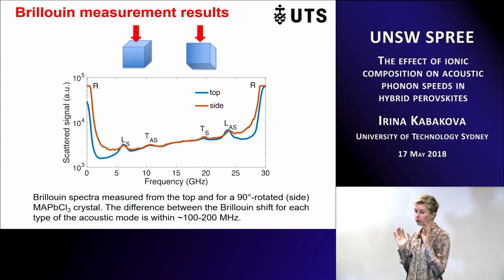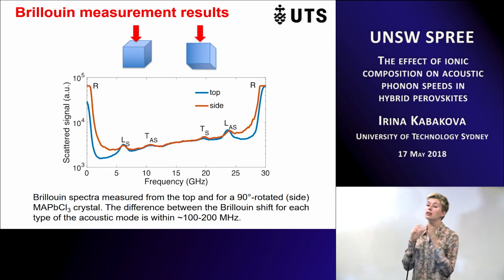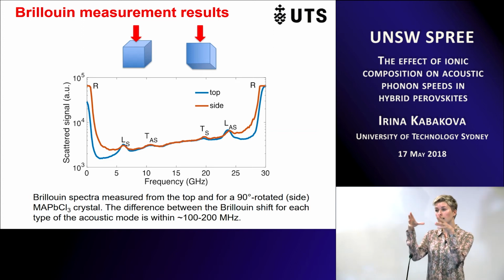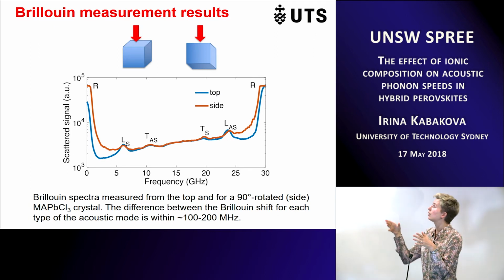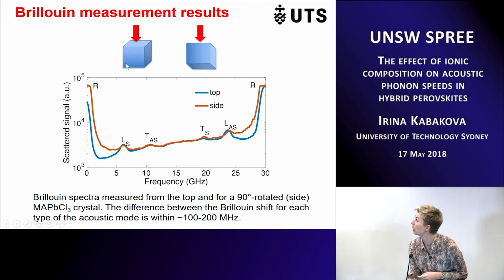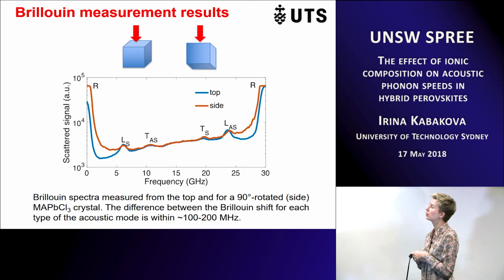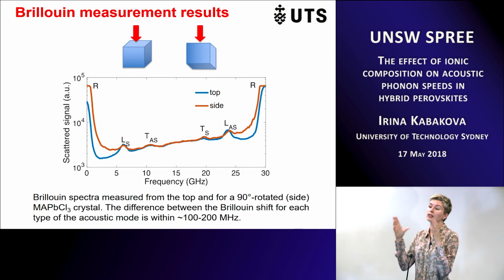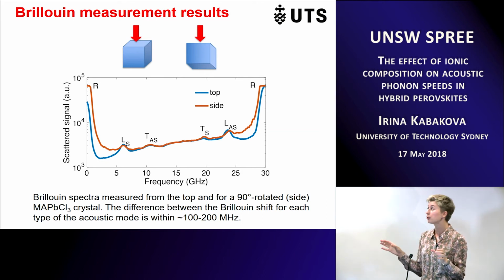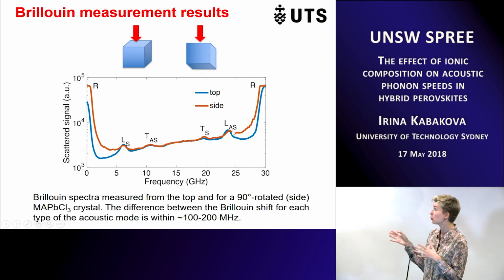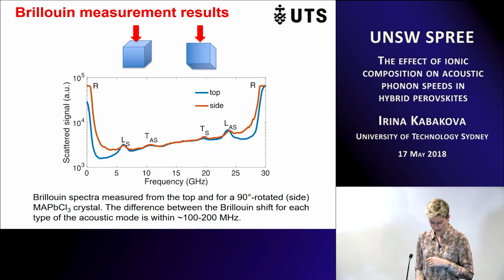What we also did, which is a very important point for doing Brillouin spectroscopy, especially because the crystals have cubic symmetry, is to align the crystal along a certain axis, because you can imagine we have all sorts of directions in the crystal, and the speed of sound will depend on the direction of the acoustic wave inside the crystal. So we tried to align it along a principal axis, so one of the sides of this cube, and we've taken the spectrum. To check that we indeed aligned our crystal along the principal axis, we turned it 90 degrees. Since it's a cubic symmetry, changing a side doesn't make any difference, and we confirmed it with measurements. For the 90-degree measurement, we obtained rather similar spectra. The variation was within the measurement error of 100 megahertz, and we were quite happy with that.